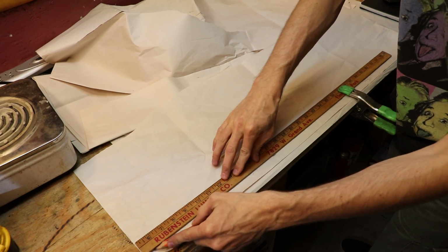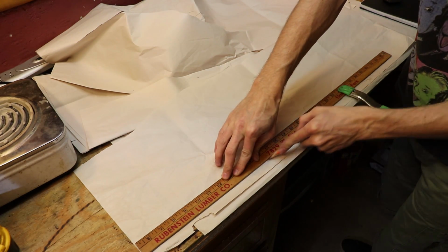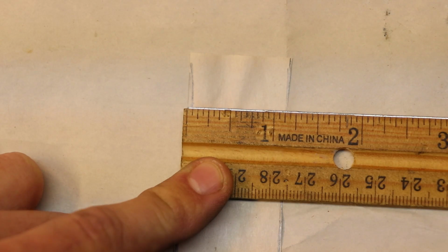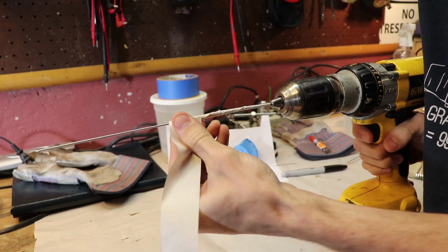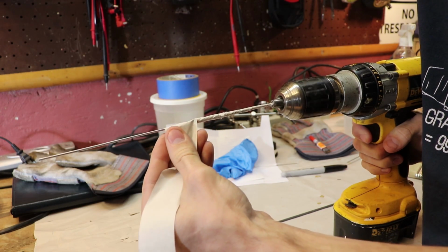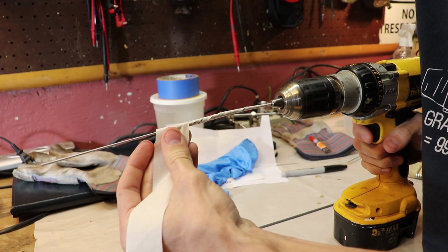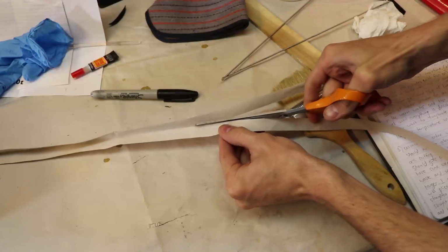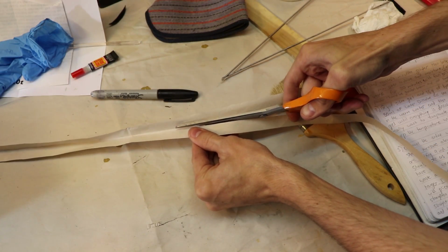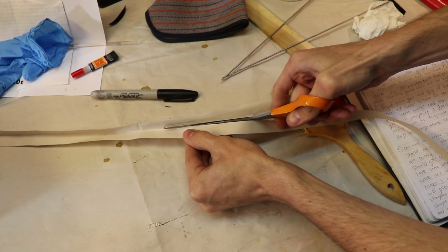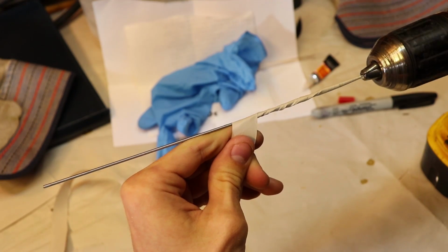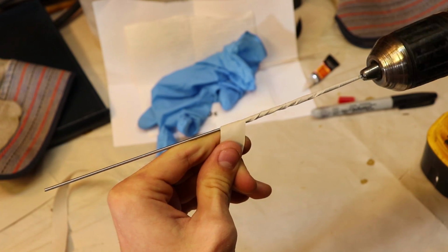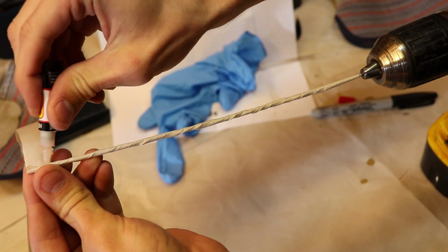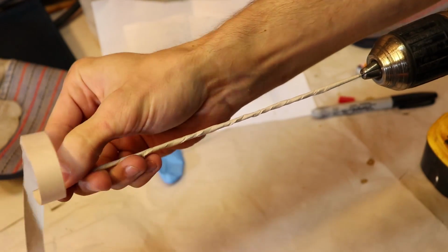The strips I made were 36 inches long, and I experimented with the width. At first, I cut inch-wide strips until the wrapping became too difficult, so less is really more in this case, and I cut the strips in half lengthwise to give me about 1/2 inch wide strips, which were much easier to wrap around the rod. I also found a little bit of super glue at the beginning and end of each wrap is really helpful.